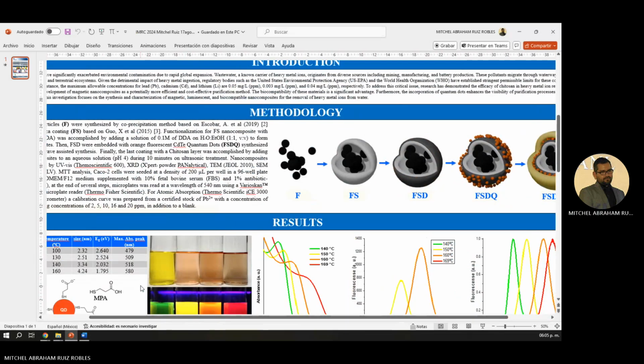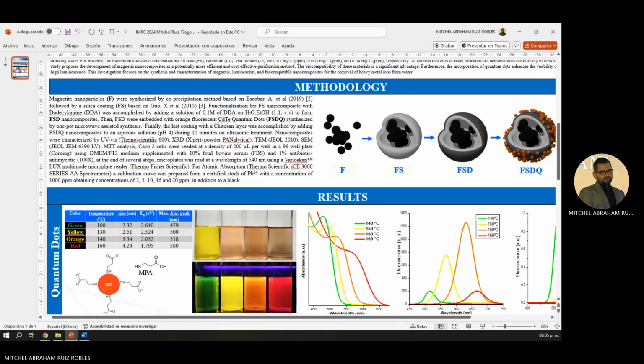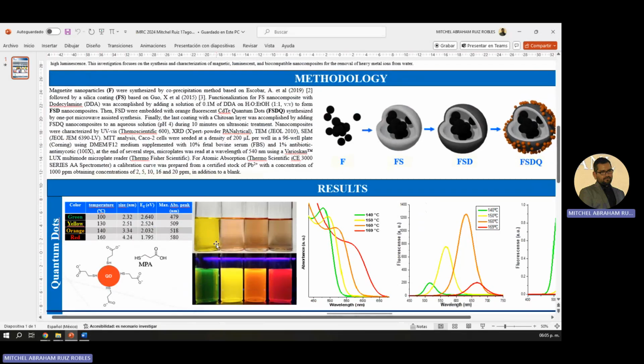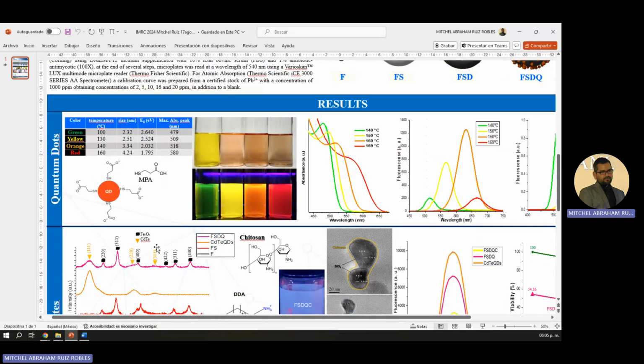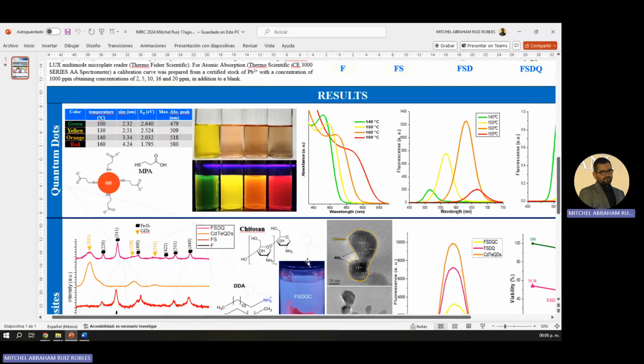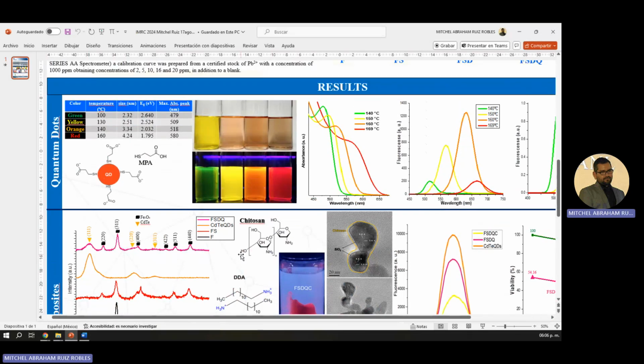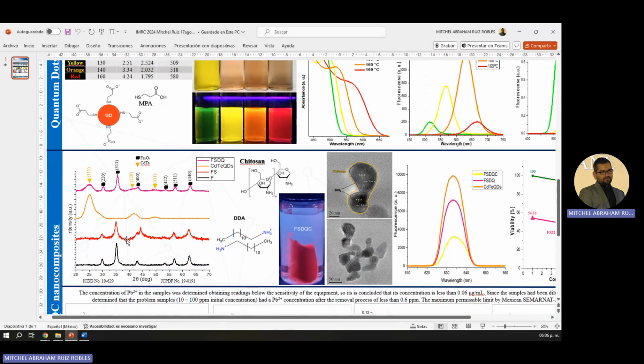Some of the results. For the results of this study, we characterized the nanocomposite with X-ray diffraction, transmission electron microscopy, as you can see here, UV fluorescence, and atomic absorption spectroscopy. The results of X-ray diffraction show that all material layers are crystalline. Every single added coating directly affects the final crystallinity. Here, we could identify diffraction peaks for CdTe quantum dots and magnetite cubic phases, as you can see here with the yellow ones and the black ones.